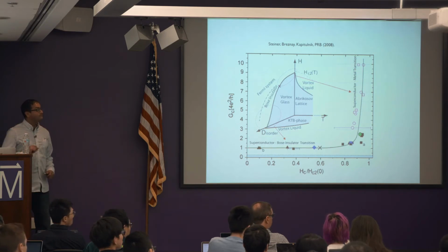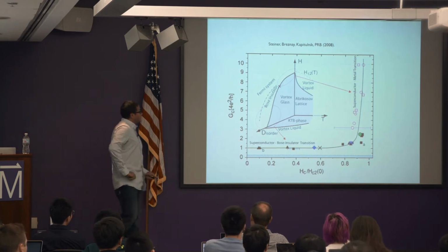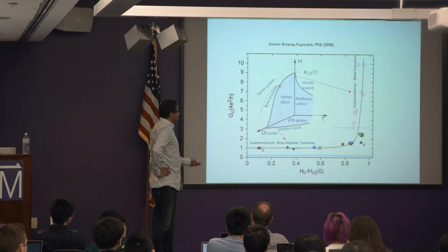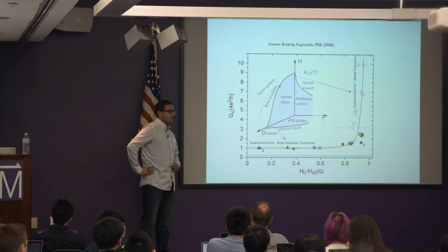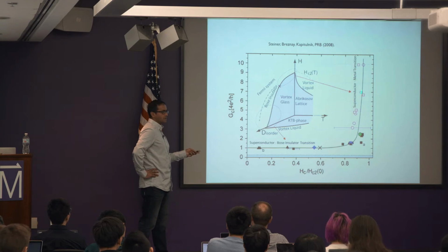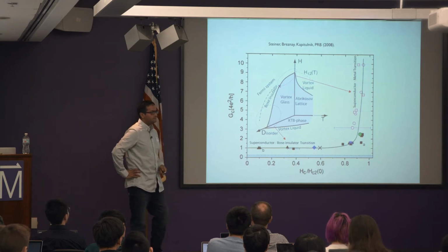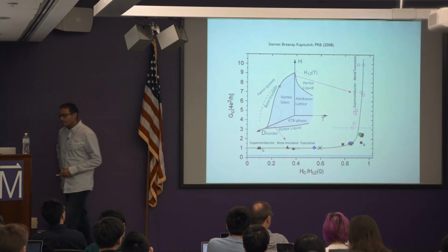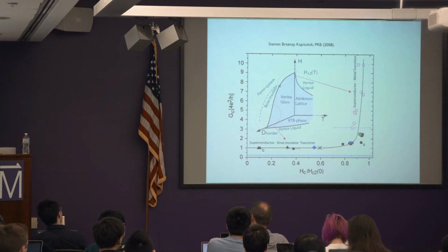So how clean are these samples on this line, these insulator transitions? In this region, if you look at temperatures above the superconducting TC, the resistance is roughly of the order of the quantum of resistance of electrons. So they're pretty dirty films. Out here, they're not. They're somewhat cleaner. Yes. Okay, so that's the phenomenology.